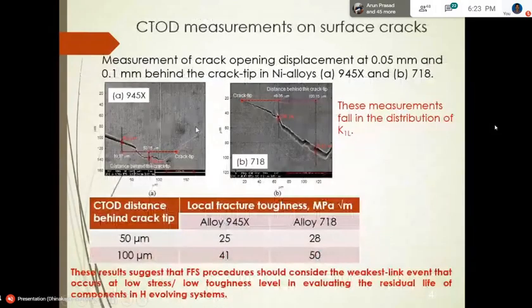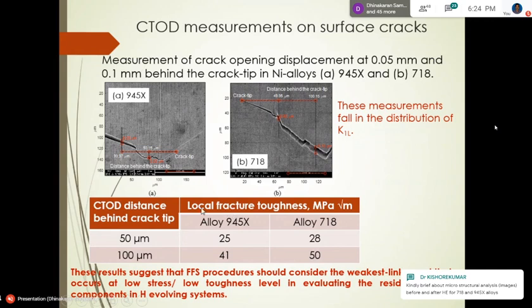And then to get some confirmation, we measured the crack tip opening displacement at the surface cracks on this specimen. This is the crack tip, and we measured at 0.05 millimeters and 0.1 millimeters, and we got this, and then plugged that value into the equation for K, the local fracture toughness, and we got something like this. 945X was slightly lower than 718, but this is a one-off measurement.